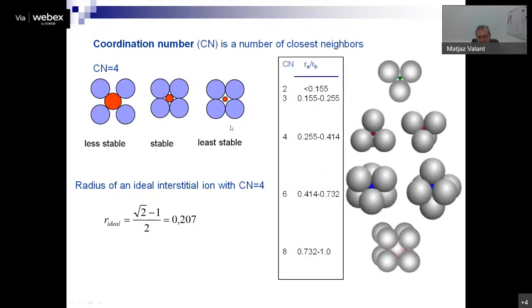The principles are the same, but geometries are a little bit different. So still, if we have very small ion in coordination with very big ions, we can expect this planar coordination, triangular coordination. Here, these are then the ratio of these two ions. If this ratio is a bit bigger, then we expect a trigonal. Then we expect this tetrahedral coordination of 4 bigger ions around one small ion, and so on and so forth. So we can even have coordination 8 when the species are pretty much of the same size.